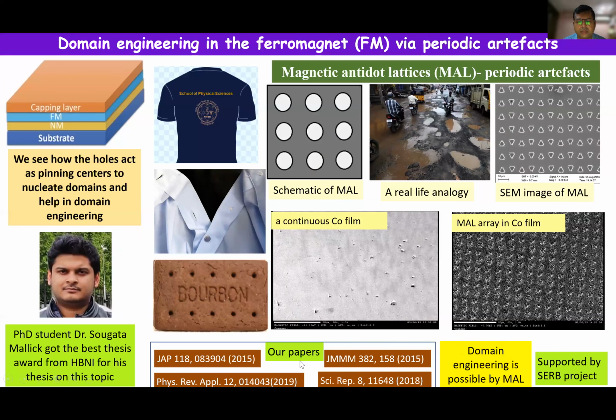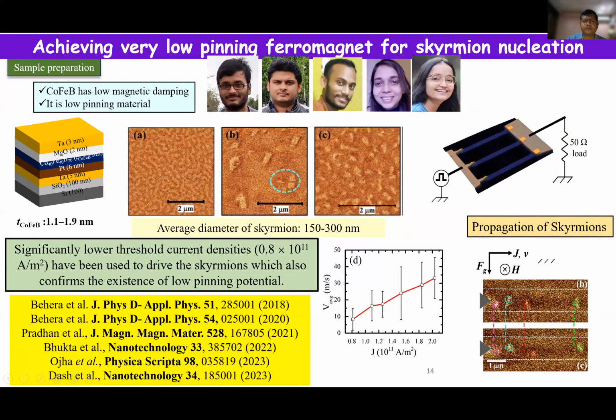Now we are also working on skyrmions and skyrmion dynamics. Here, the point is, if you design your architecture in such a way that you have strong Dzyaloshinskii-Moriya interaction at the interface, then you can induce skyrmions. Of course, there are other methodologies too, and you can start with the labyrinth domains and break them into skyrmions by applying some field. Obviously, there is high interest in zero-field skyrmions at room temperature.